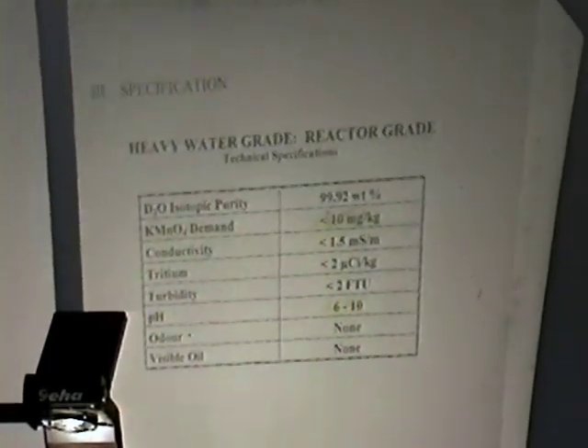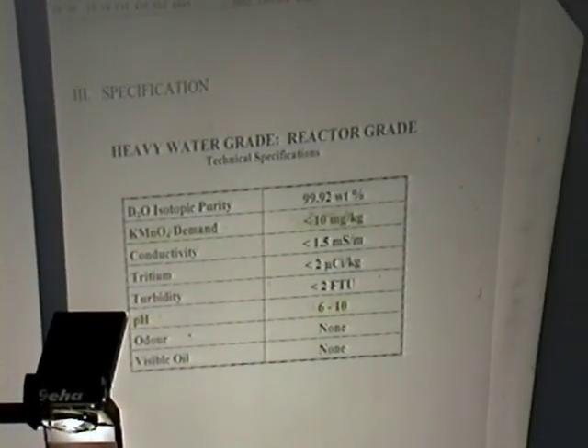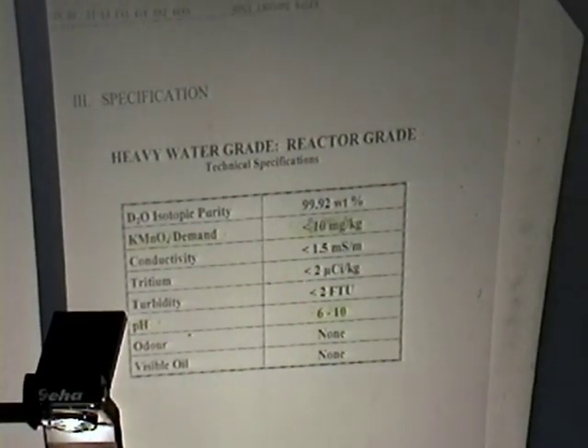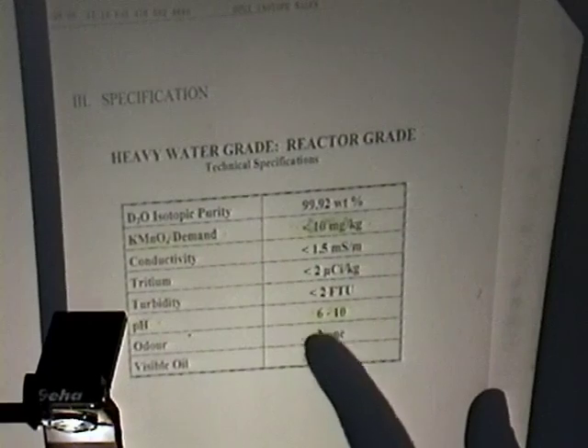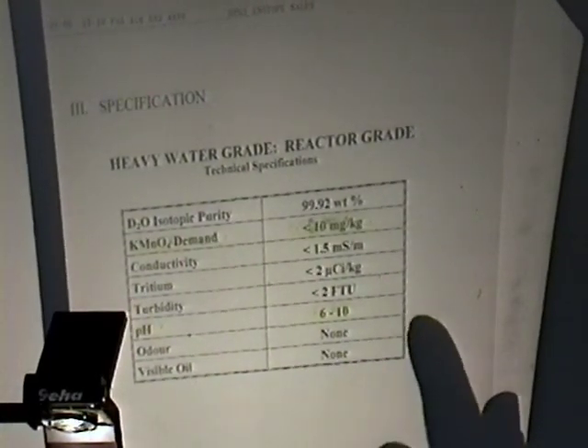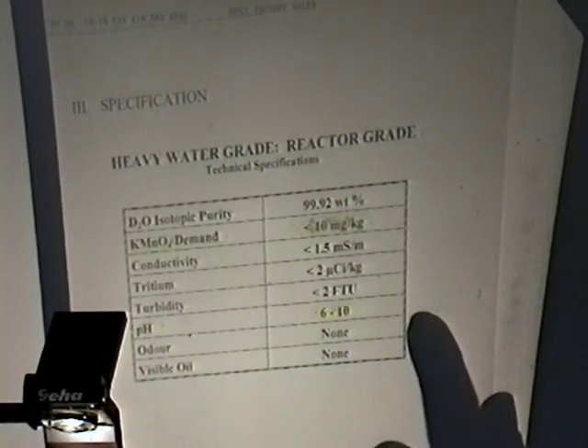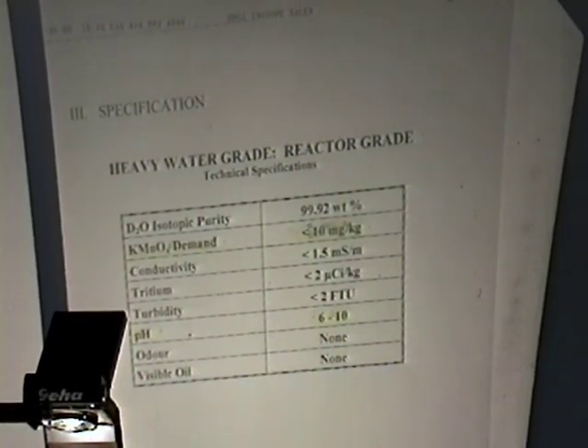Just to remember the isotopic purity of high purity heavy water, reactor grade. The purity is very good, 99.92. But the permanganate demand is quite large, 10 milligram per kilogram. It means that in the closed bottle, from the start, just out of the company, there are several bacteria. Conductivity is very good, but easy to improve. The pH can be between 6 and 10. It's strong proof that in heavy water there are a lot of unknown materials that can make this large variation of the pH.